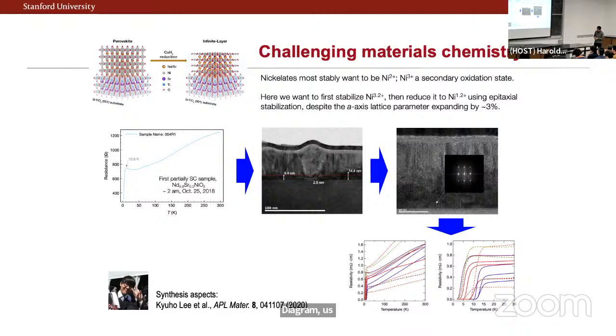So we tried doping the system, and the very first hint of anything interesting happened around 2 a.m. Fall of 2018. At least in my lab, nothing interesting actually happens during business hours. So Denver made this very exciting discovery, but it was far from a real discovery in the sense that this was not a real zero resistance state. It was a little bit of a glitch.